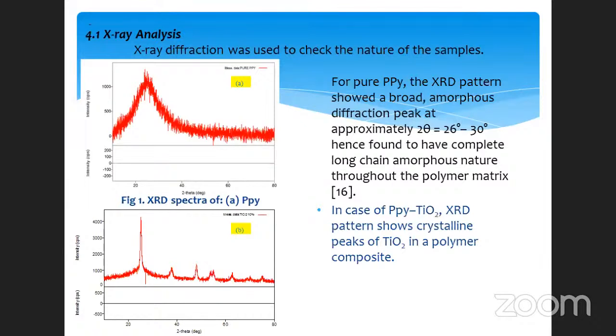Kindly pay attention to the first graph, the XRD spectra of polypyrrole. For pure polypyrrole, the XRD pattern shows a broad amorphous peak at 2 theta equal to 26 to 30 degrees. This shows a halo nature, and it shows the long chain amorphous nature of the polypyrrole throughout the polymer matrix. And then when it is doped with TiO2, the XRD pattern shows crystalline nature inside the conducting polymer polypyrrole. Next, please.